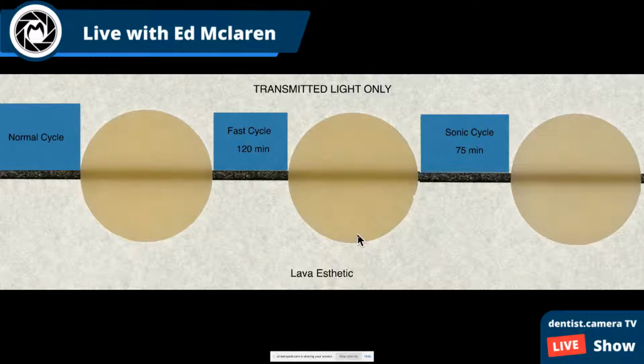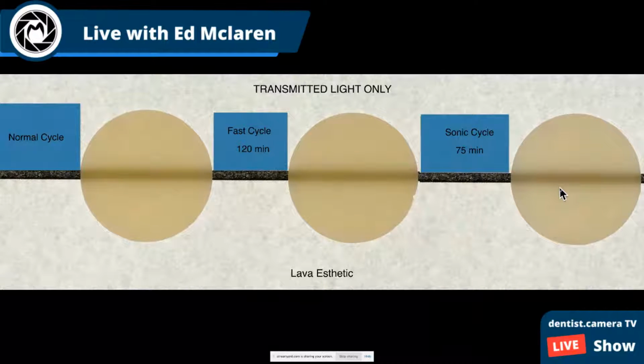What we found with most materials, you could shorten the firing cycle to 120 minutes, in and out, from the time you put it in the oven to the time you can start working on it, okay? You need to think about heat up, cool down, and all that stuff, okay? Sonic cycle is what I call it. And most of the Tosoh materials, you couldn't go below that. You start to lose chroma, you start to lose translucency.